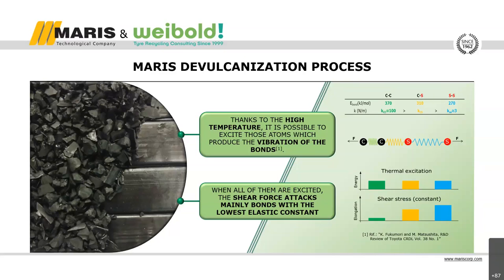small, it's quite small. The extruder provides to the material to be devulcanized both thermal and mechanical energy. In this way, thanks to the high temperature, it is possible to excite those atoms which produce the vibration of the bonds. At this point, the shear force provided from the screw attacks mainly the bond with the lowest elastic constant. If we imagine the bond like a spring, in a certain point of the screw, when the shear forces are constant, the bonds with the lowest elastic constant may become fully elongated to their limited extensibility.